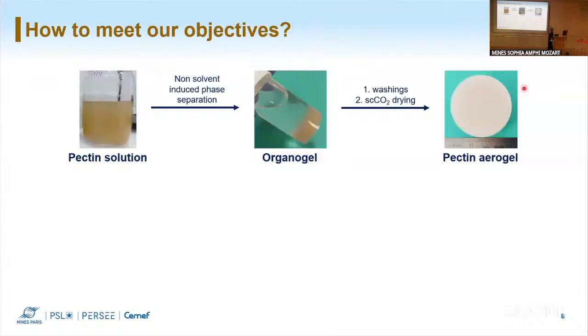And what can we do to meet our goals? Here is the general scheme of pectin aerogel fabrication. We start from a pectin aqueous solution. We create a gel by non-solvent induced phase separation, and then we dry with supercritical carbon dioxide to obtain our aerogel material.